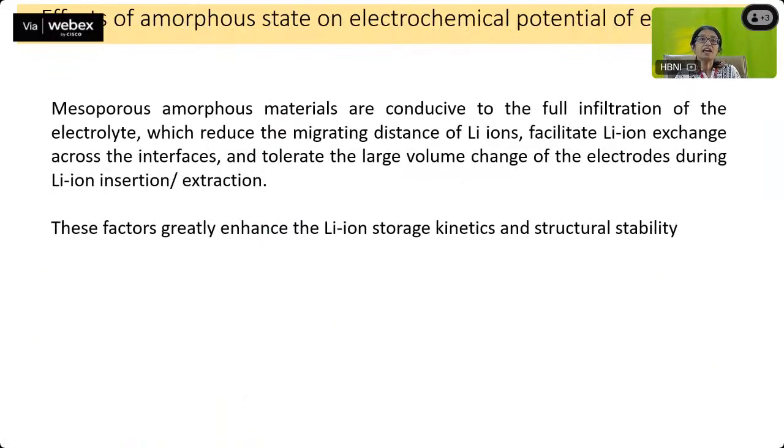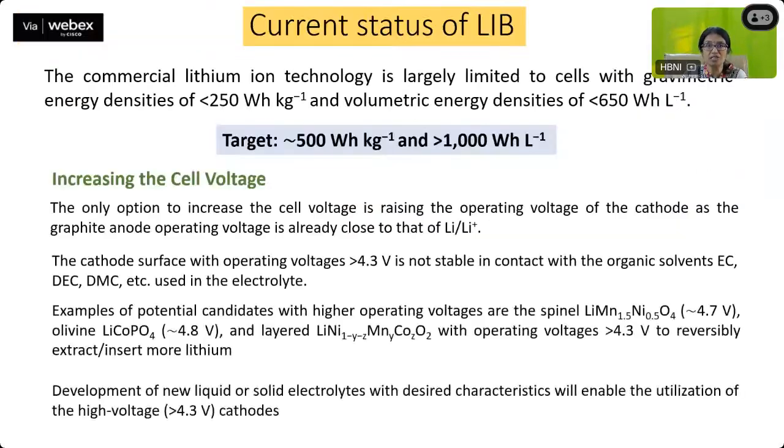Then the effect of the amorphous state on the electrochemical potential of electrodes. Mesoporous amorphous materials are conducive to the full infiltration of the electrolyte, which reduces the migrating distance of the lithium ions, facilitating lithium ion exchange across the interfaces, and tolerating the large volume change of the electrodes during lithium ion insertion and extraction. And these factors greatly enhance the lithium ion storage kinetics and structural stability.